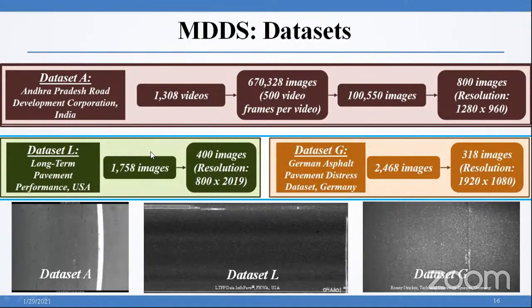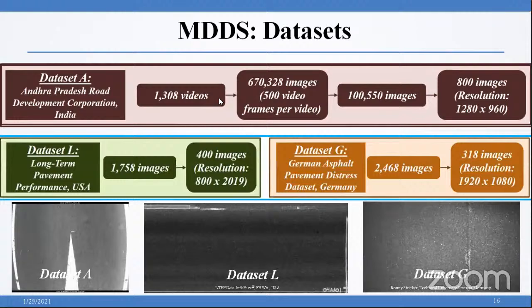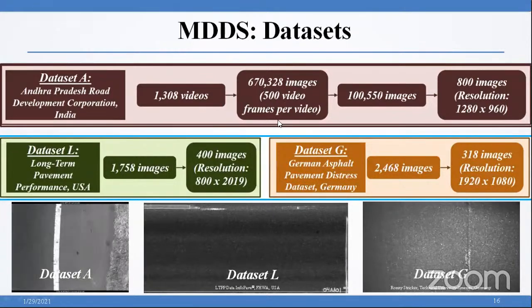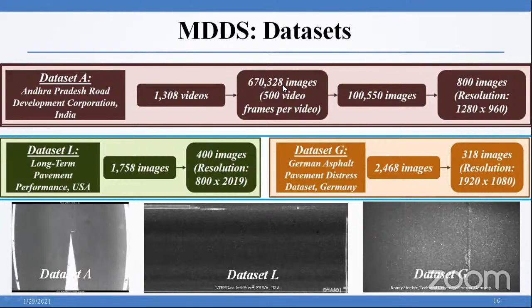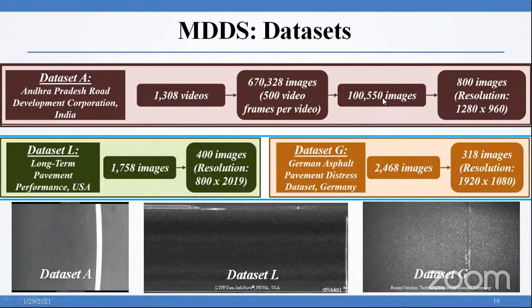So dataset A was collected from Andhra Pradesh Road Development Corporation. We have collected 1,308 videos of 541 road sections in the Andhra Pradesh state, and each video had about 500 video frames. We wrote a MATLAB code for segmentation, and after performing the segmentation, we obtained 6,70,328 images. Since the data set is huge, we considered only 15% of the total images, which is 1,00,550, for this study. Out of those, after analyzing each and every image, we found 800 images which had visible distresses.